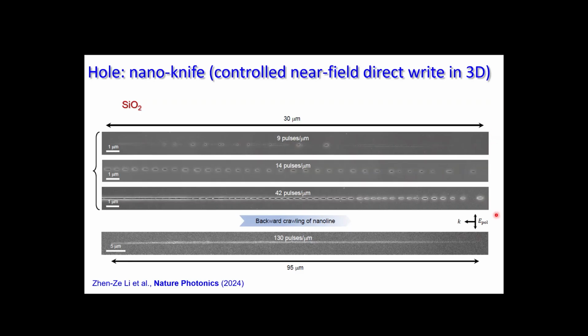The beam is propagating from right to left. And the scanning speed means that we are scanning the sample out of plane, out of this image plane. So if it's 9 pulses, it means we are scanning so slowly that until we go 1 micron, 9 pulses will overlap. And if we are scanning even more slowly, like 42 pulses for 1 micron, we begin to see how the pattern is evolving from kind of random modified regions into regions which are interconnecting with each other.